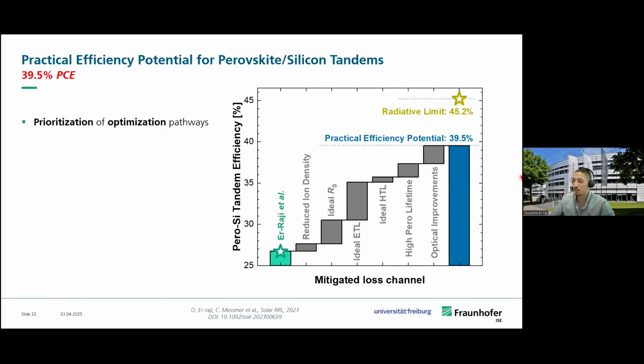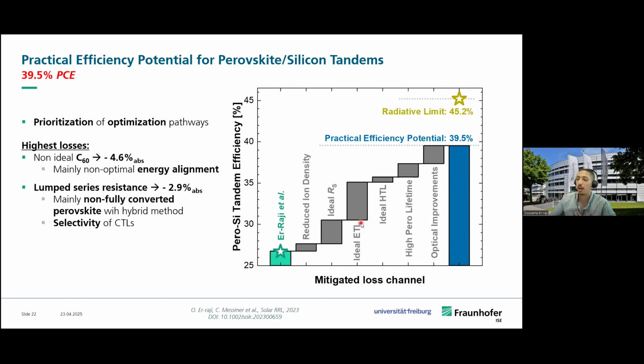This allows us to construct such a graph where, starting from our experimental device with 26.7%, we have different loss channels, and we can directly say, okay, if I want the highest efficiency gain, then I need to tackle this issue here, which is non-ideal ETL, for example, as we saw, the perovskite C60 interface. And from this, we saw that for our device, the highest losses were at the ETL interface and the lumped series resistance. Also, by cumulatively mitigating all the losses that we have in the device, we saw that a practical efficiency potential of 39.5% could be achieved.